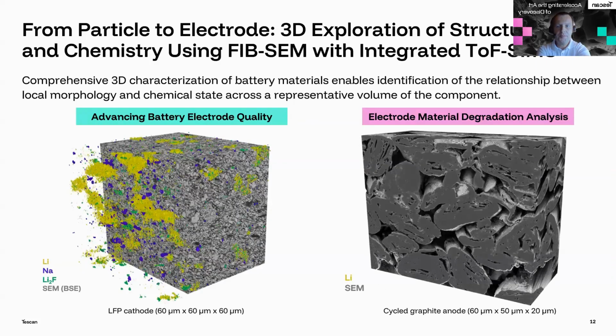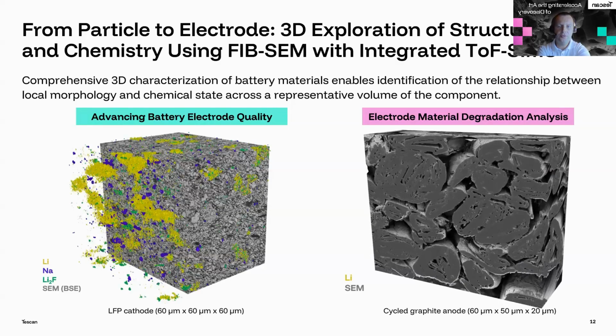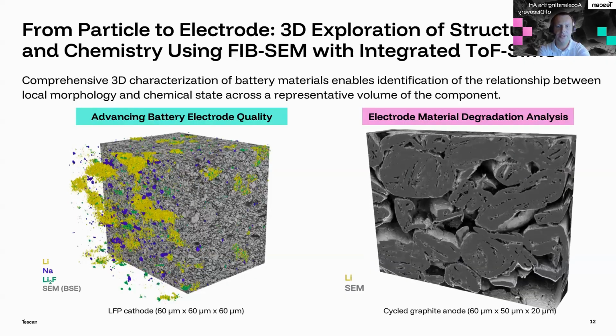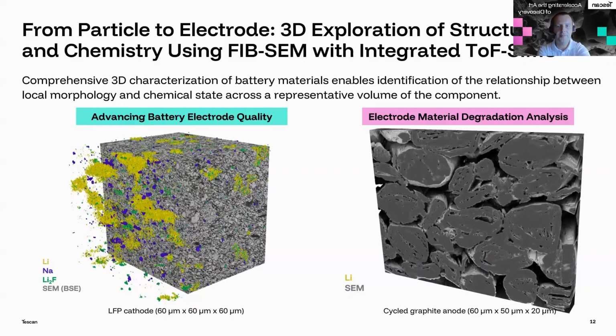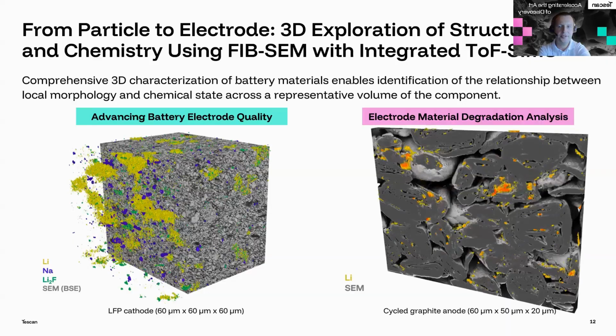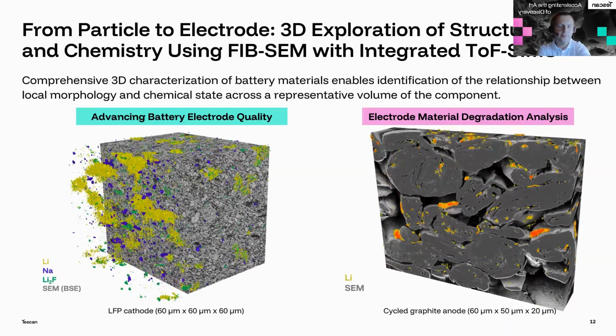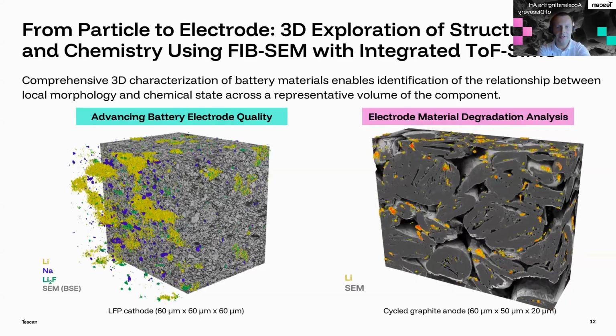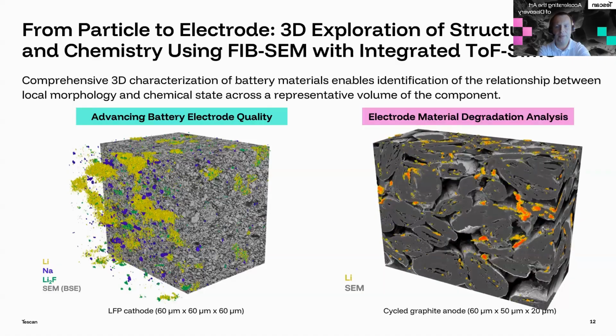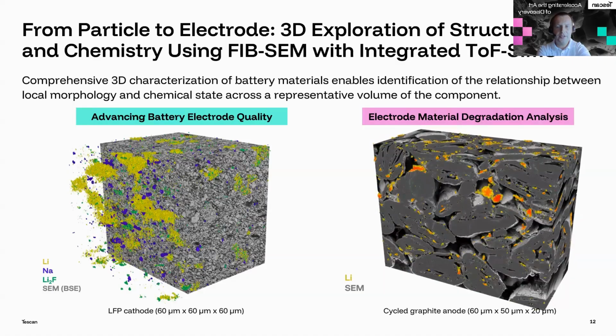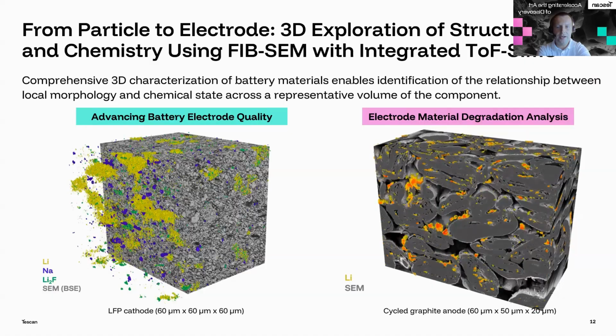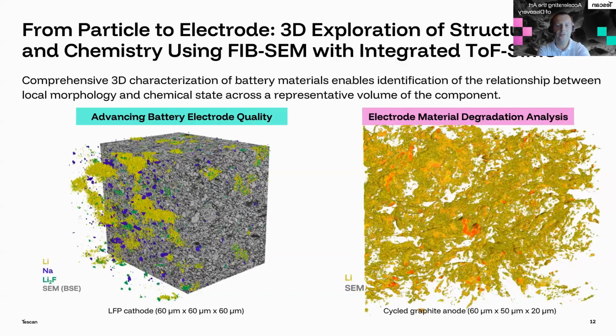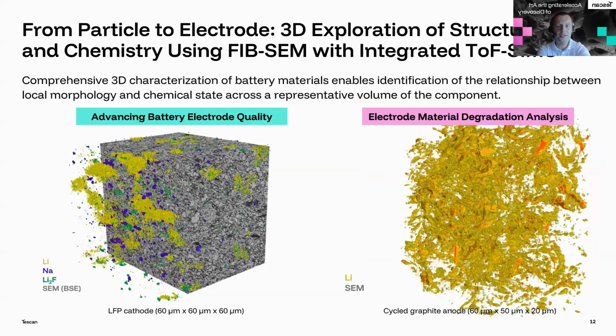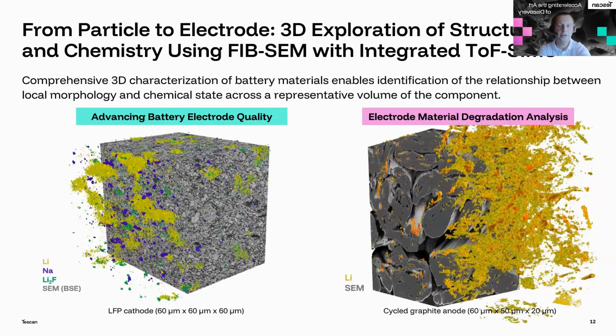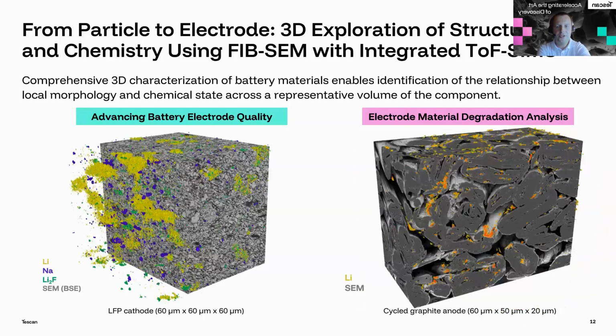With the FIB-SEM instrument, it is possible not only to prepare large cross-sections across the full electrode thickness by FIB milling for subsequent subsurface observation, but also to perform large-scale FIB-SEM tomography, so to study the 3D distribution of battery materials. And when integrated with time-of-flight secondary ion mass spectrometry, TOF-SIMS, tomography provides not only structural, but also chemical information. And this enables, for instance, highly sensitive analysis of lithium distribution in cycled electrodes to reveal the relationship between the chemical composition and electrode degradation, to localize trapped lithium, and to study the distribution of composition of the solid electrolyte interface.